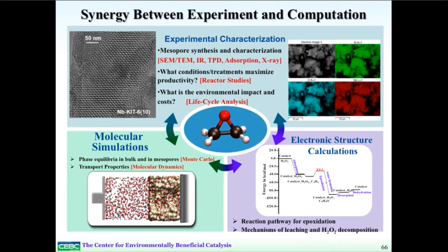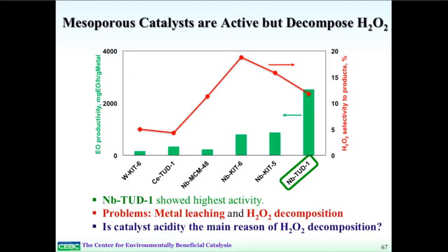My group is involved in a lot of molecular simulations to try and understand how these particular solvent materials, liquid solvent materials, behave when you get inside the pore. That's not that experimentally accessible. And then we can do electronic structure calculations to understand the reaction pathway. So there have been a number of studies. The first thing that they found is that using these mesoporous catalysts, we can get significant activity, but one problem that we have is that these tend to decompose the H2O2, the hydrogen peroxide. And if you look here at the H2O2 selectivity to product, you can see that basically only about 10% of the H2O2 is being used.